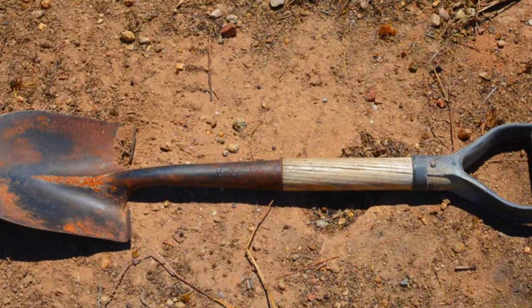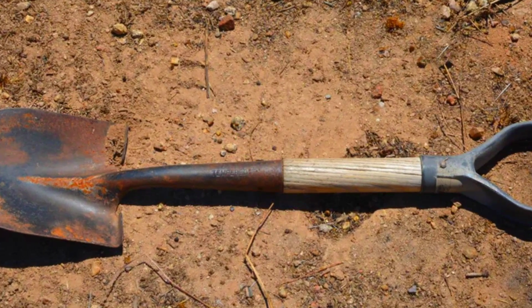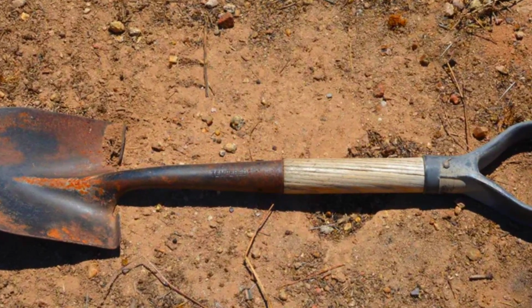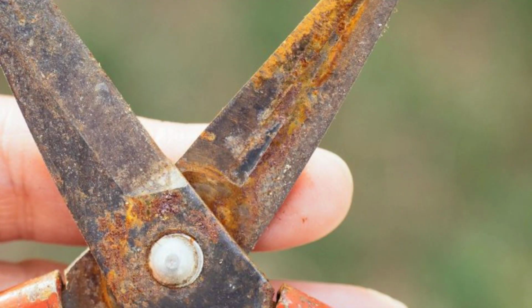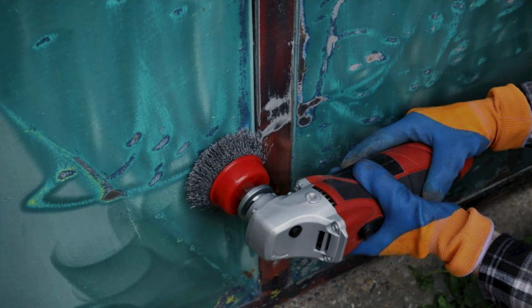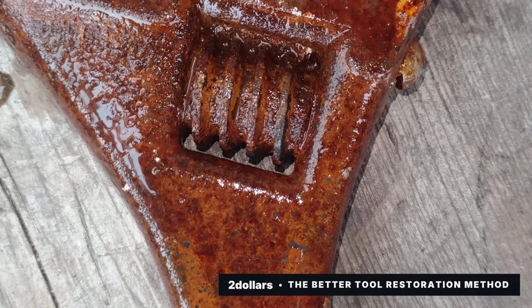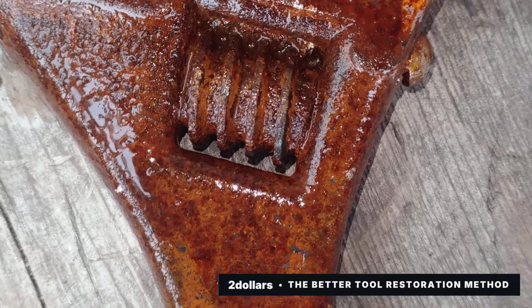The standard advice is a wire wheel on a drill, and it does clear the rust, along with a layer of good steel, and it leaves the surface bare and rougher than it was, which is precisely the condition rust likes best. Then a spray of water displacing oil that has evaporated off by the following month. There is a way to take rust off a tool for about $2 without removing any metal at all, and to leave a surface behind that does not start again.